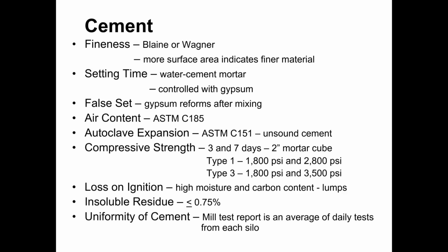Right, air content is another item that's indicated on the mill report that can be determined by ASTM C185. Autoclave expansion is covered by ASTM C151. Autoclave expansion is an indication of unsound cement. We don't really have a problem with unsound cement in the concrete industry today. In years past, it has been an issue, but with tighter controls on the materials that go into the cement and the cement manufacturing process, the occurrence of unsound cement has become almost non-existent.